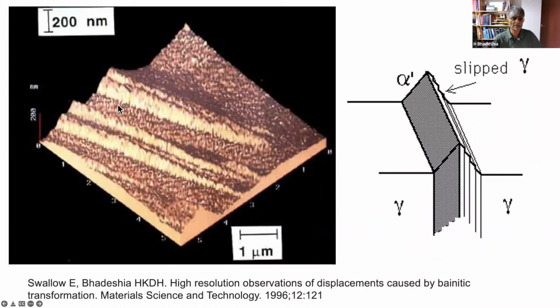Okay. However, there is something special. The austenite adjacent to this plate is also curved. And what's happening is that at the temperatures where bainite forms, you get a plastic relaxation of the adjacent austenite because the strains are too large to accommodate at high temperatures where the parent phase is not strong. So you get this accommodation of the shear deformation, and that partly relieves the strain energy.